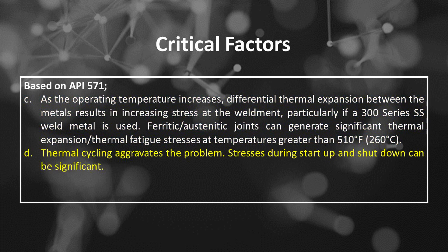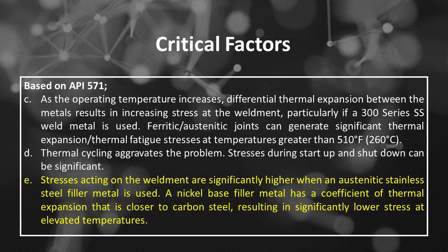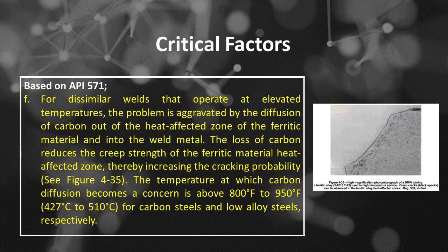Stresses during startup and shutdown can be significant. The fifth is stresses acting on the weldment are significantly higher when an austenitic stainless steel filler metal is used. A nickel base filler metal has a coefficient of thermal expansion that is closer to carbon steel, resulting in significantly lower stress at elevated temperatures. The sixth is for dissimilar welds that operate at elevated temperatures. The problem is aggravated by the diffusion of carbon out of the heat-affected zone of the ferritic material and into the weld metal. The loss of carbon reduces the creep strength of the ferritic material heat-affected zone, thereby increasing the cracking probability.